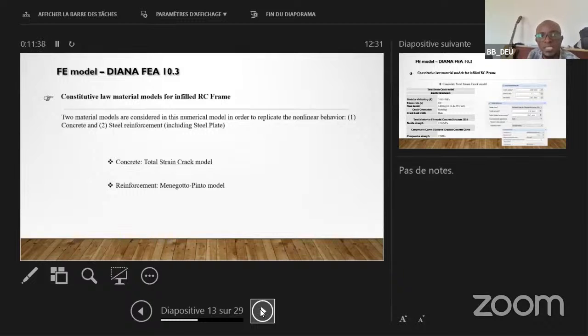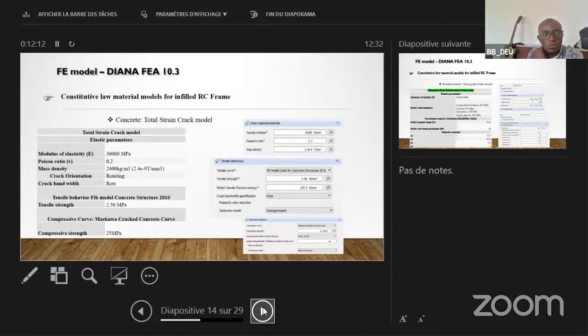For the constitutive law material model, we define for concrete the total strain crack model. This model describes well the propagation of cracks for the material. And for reinforcement, we use the Menegotto-Pinto model that shows good agreement for the cyclic curve. Here we define all parameters for the total strain crack.